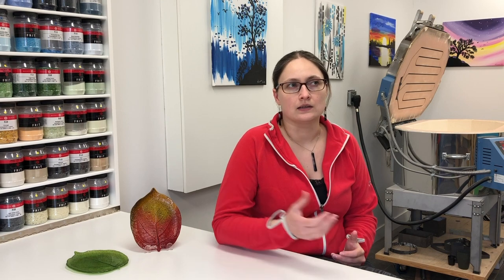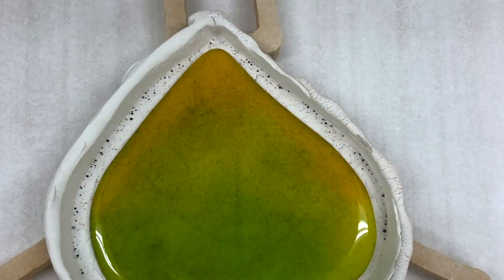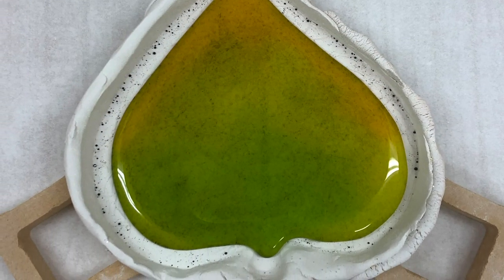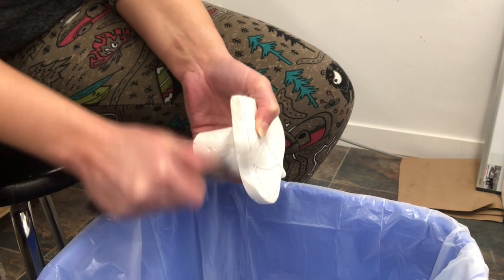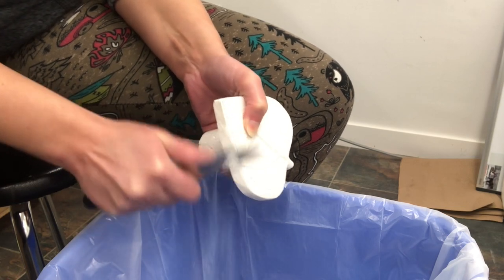A second trip to Alan's studio, we were able to get some usable molds to check the resulting size. The clay shrinks as it dries, which was an unknown variable to me, and the glass also shrinks as it's casting in the mold — the air spaces between the particles of glass squeeze out, so the glass can shrink in the mold up to a quarter of an inch. After a trial run I was able to fine-tune the size of the plaster stamp, adjusting the resulting size of the glass piece coming out of the mold.